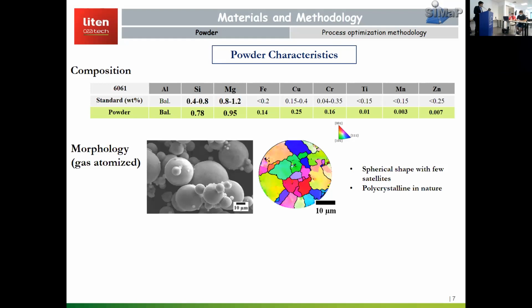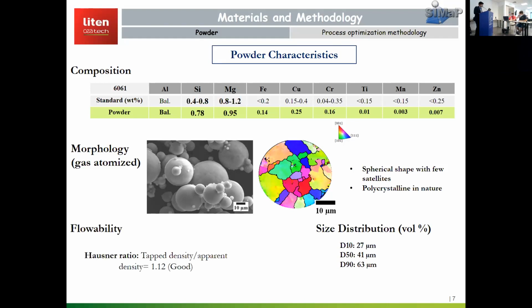In terms of morphology, for the gas atomized powder, we clearly see that you have some satellites, you have spherical shape of the powder, and the powder morphology is polycrystalline in nature. In terms of size distribution, the powder was quite good in terms of the requirement in L-PBF, which is from 20 to 60 microns, and we had that size distribution achieved with our powder.